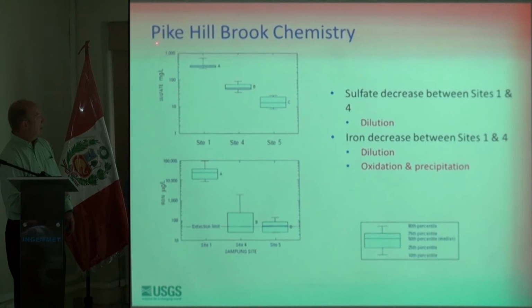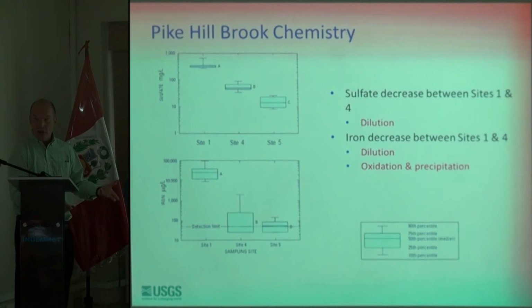When you look at sulfate concentrations at these four sites, you can get a general sense of the role that dilution has in these sites. But when you look at iron, you don't see the same sort of trend. You see a more rapid drop in iron concentrations. It's fairly farther downstream. Again, this is a reflection of those iron precipitation reactions that we saw were so important at the Elizabeth mine.